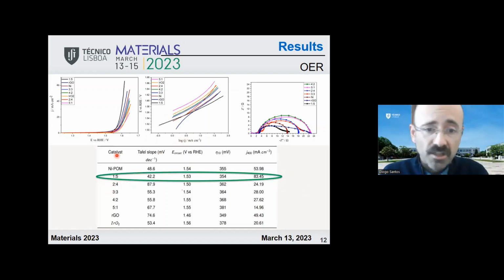Then, knowing that the nickel POM was the most interesting material, we decided to test different ratios between this POM and reduced graphene oxide. So what we did was to change the ratio between these two components in the prepared composites from 1 part of POM to 5 parts of RGO until 5 parts of POM to 1 part of RGO.